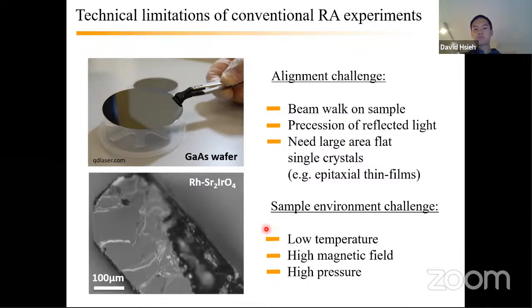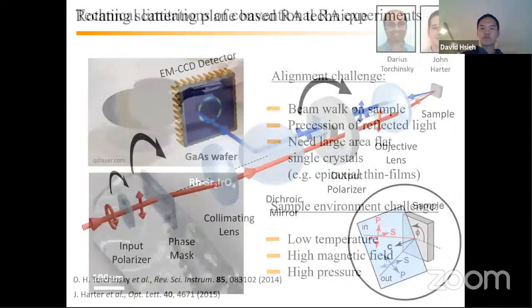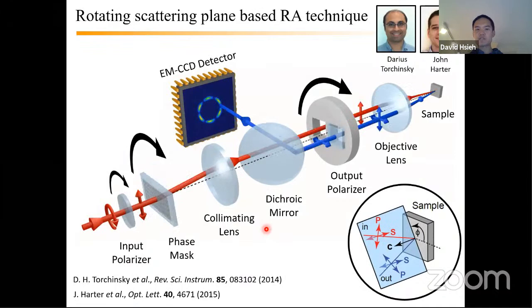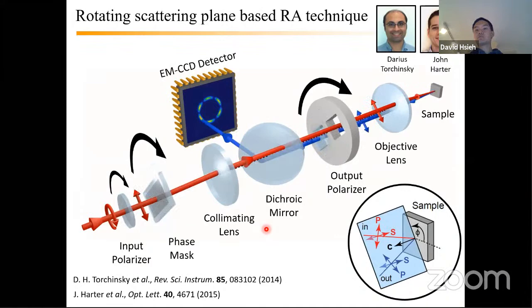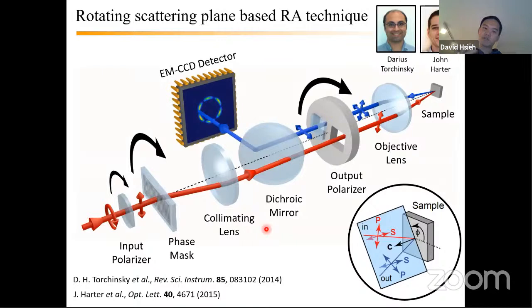Moreover, oftentimes we want to do things at low temperatures or extreme environments like high fields and high pressures. And it becomes very hard in those environments to rotate your crystal, right? If you embed your system in, for example, a diamond anvil cell for high pressures, it's very challenging to rotate that cell mechanically. Okay, and so we developed a few years ago a few generations of a setup that enable you to keep the sample stationary, okay, so that you can accommodate these extreme environments and just rotate the scattering plane externally, but do that in a very precise way, okay?